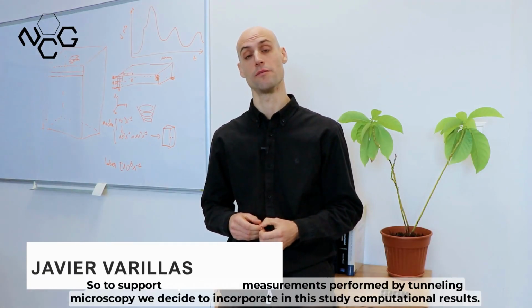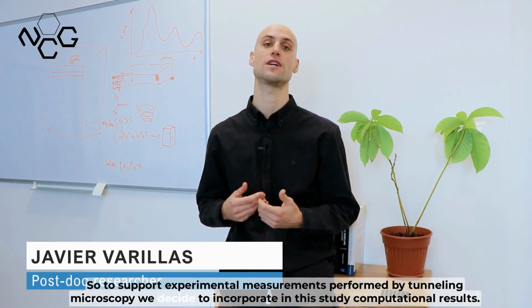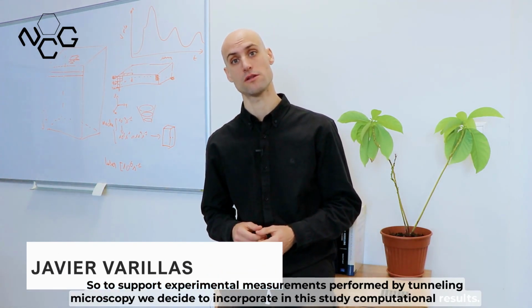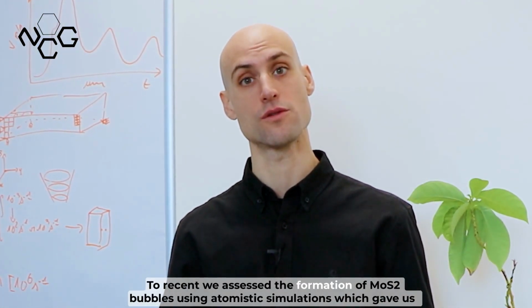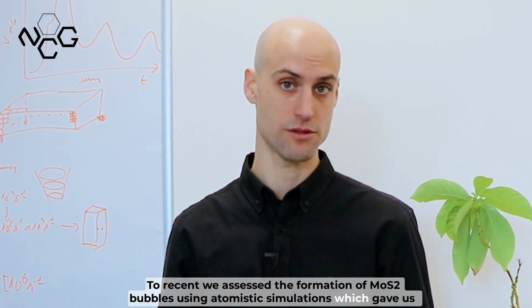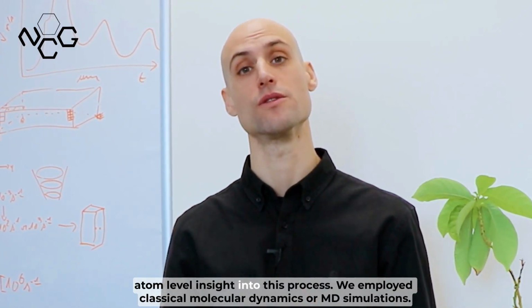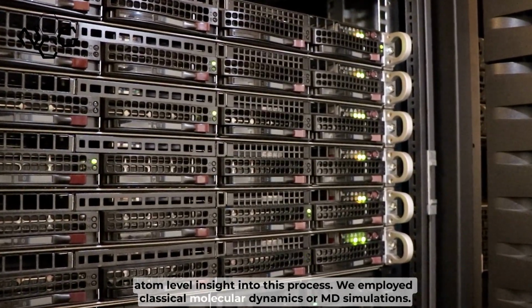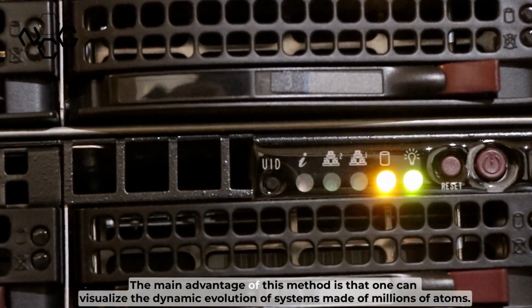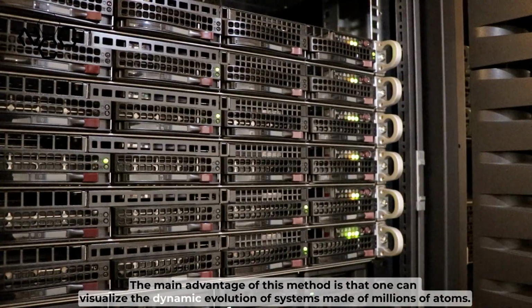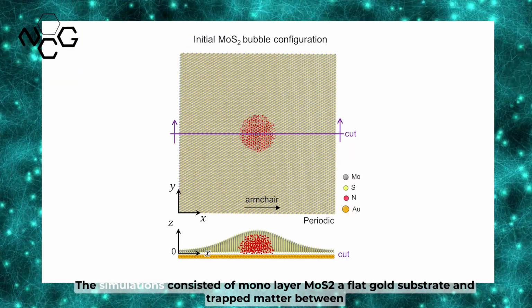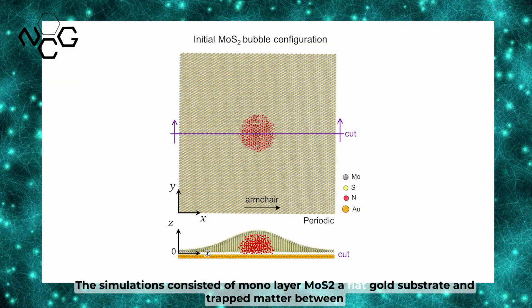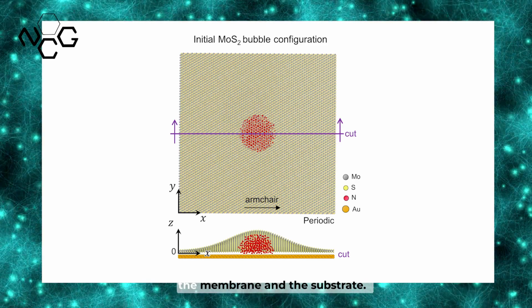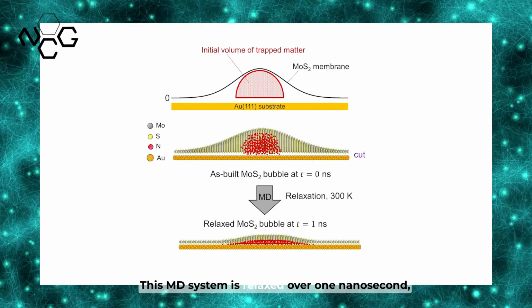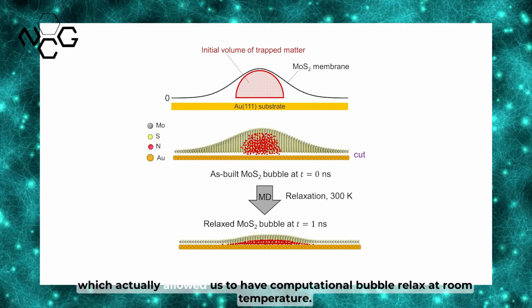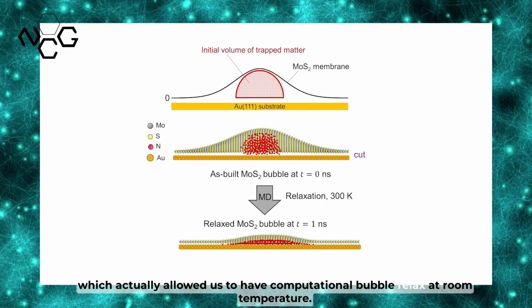So, to support the experimental measurements performed by tunneling microscopy, we decided to incorporate computational results in this study. To this end, we assessed the formation of MoS2 bubbles using atomistic simulations, which gave us atom-level insight into this process. We employed classical molecular dynamics, or MD simulations. The main advantage of this method is that one can visualize the dynamic evolution of systems made of millions of atoms. The simulations consisted of monolayer MoS2, a flat gold substrate, and trapped matter between the membrane and the substrate. This MD system is relaxed over 1 nanosecond, which allowed the computational bubble to relax at room temperature.